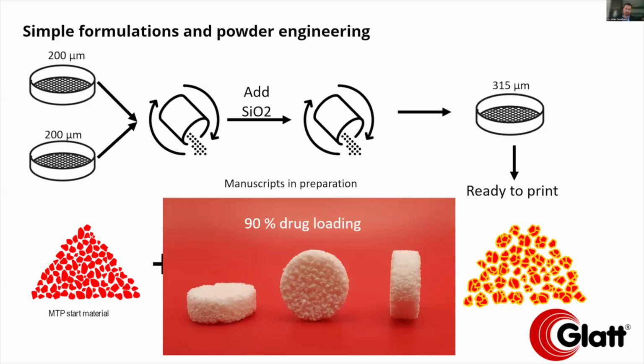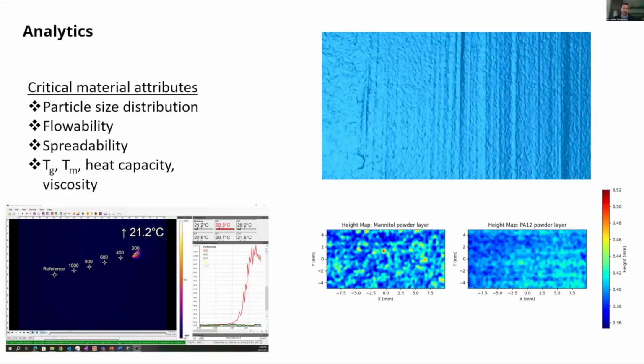And we're also learning a lot more about the powder properties that are important for pharmaceutical additive manufacturing. So of course, the particle size distribution is of key importance, so is the flowability. But we are now also using 3D imaging to determine the roughness of the surface, and also using it for error detection. So this you see on the bottom right. So you have the PA12 powder, highly engineered powder for SLS printing, very smooth surface, very little variation in the height. Whereas if we use mannitol, as shown in this picture, you see a much rougher surface structure with a wider particle size distribution and also a less homogeneous spreadability.